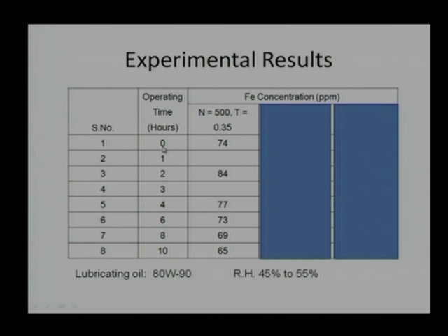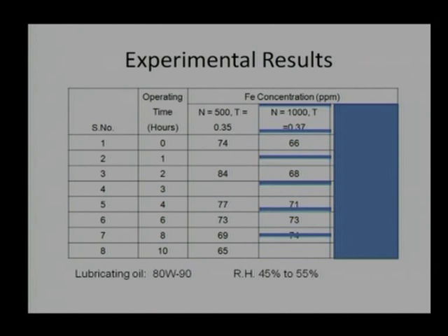We can conduct this kind of experiment without much problem. Just after starting the experiment, we took the reading and found 74 ppm as iron concentration. After 2 hours of operation, this increased to 84. After that, it remains almost steady: 77, 73, 69, 65. The interesting thing is that it is always in our mind that after that, if I continue to operate, this percentage should come down, because the bathtub curve says clearly that initially it will be high, subsequently it will come down, but it did not happen to us.